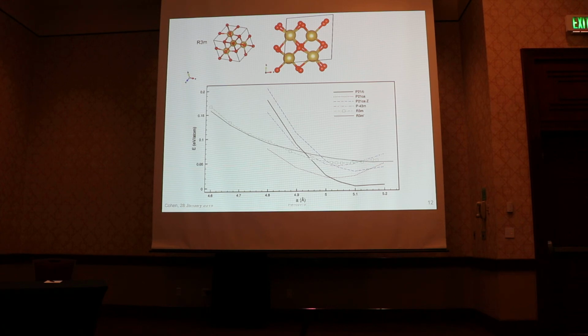Also shown here is a nonpolar cubic phase, which is interesting because it's piezoelectric, and I don't think people have talked about this. I find it to be also one of the low energy phases: this P-bar-4-3m structure, which is also a relative of all these, a distortion of the fluorite structure. It's interesting because it's cubic, so it's not polar, but it doesn't have inversion symmetry, so it's a piezoelectric structure.